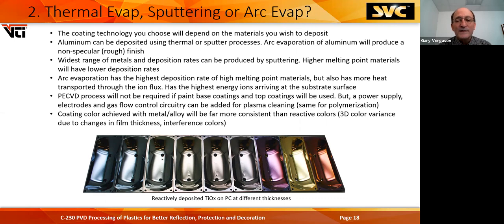The widest range of metals and deposition rates can be produced by sputtering. Higher melting point materials would be a little slower deposition rate, and higher melting point is where the cathodic arc really has an advantage, a very highly charged flux. The plasma enhanced CVD process is not required if you're using paint coatings, but with the electrodes and the gas flow control circuitry, you can add plasma polymerization in almost any system. And it's the same electrodes and power supplies used for plasma cleaning and for doing the polymerization. As you can see from the slides down below, which are primarily titanium oxide coatings at different thicknesses, you can get quite a wide variety of colors.